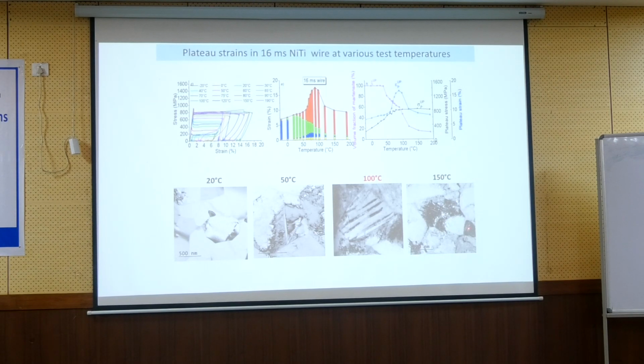So in this case, we can analyze the strains, and we look into the material by transmission electron microscopy. So if we did that, so at room temperature, which is somewhere the green curve. The green curve here, it's perfectly reversible. This is the green curve. So if we look into the microstructure after, you will find practically no dislocations, no damage.